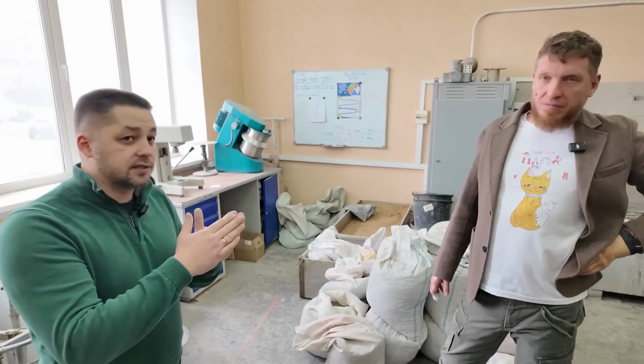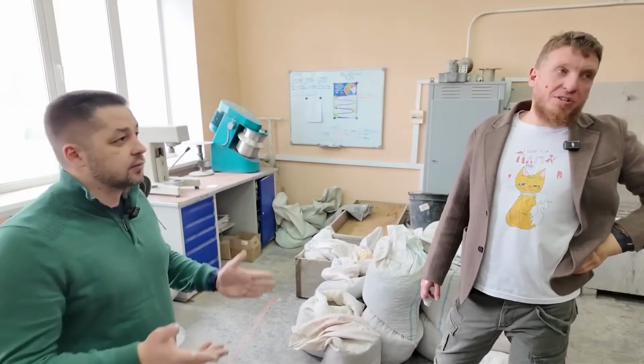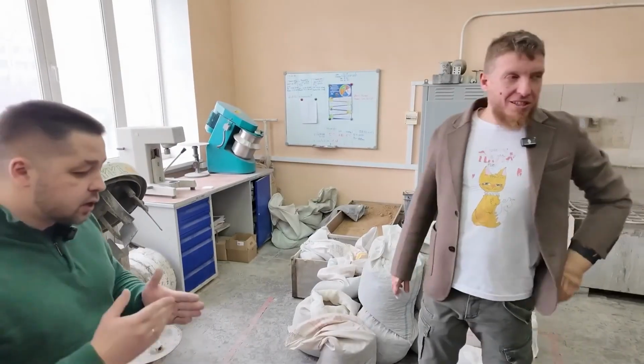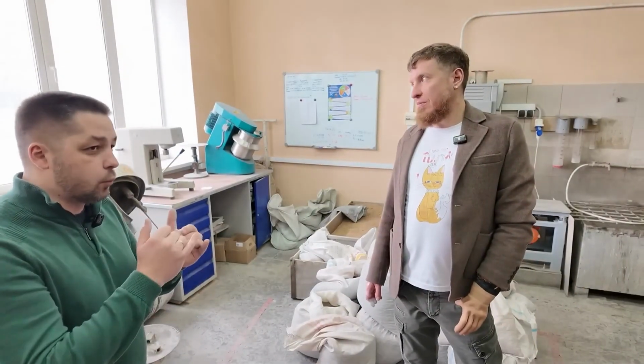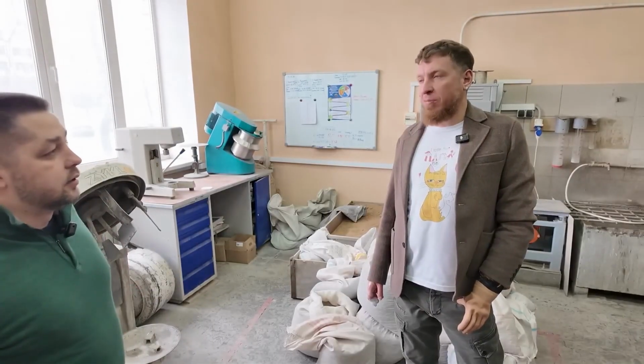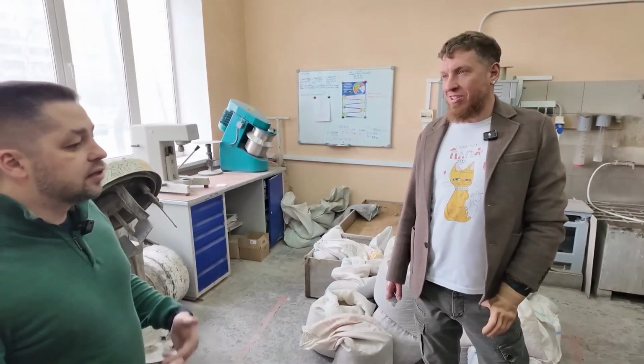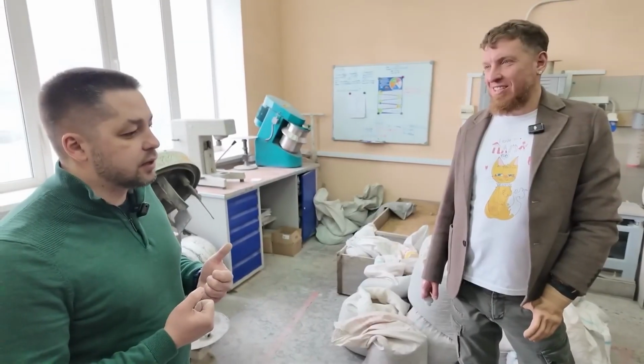When the concrete hardens, it basically ends up full of these micropores. These pores act as dampers. A crack forms during the process, and it enters the pore. If you drill in, this happens. The crack runs and hits a pore. It gets sealed up, so that it doesn't keep spreading.